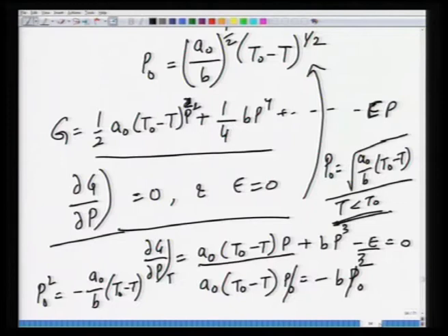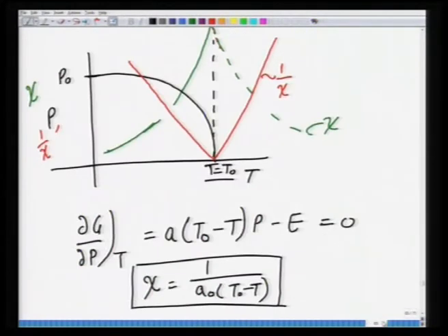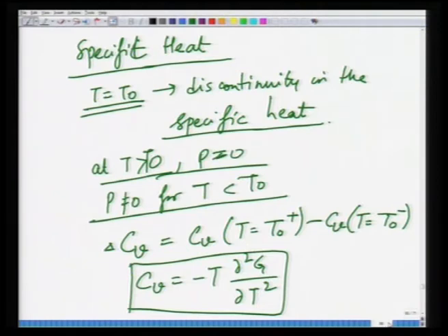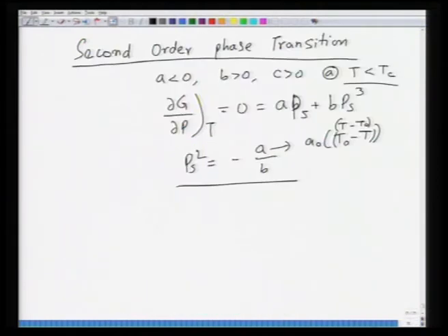From that you get an expression for Ps squared, the saturation polarization near Tc, and then we got the susceptibility near the transition: below Tc and above Tc as 1 over A naught into T naught minus T. Near T naught it goes to very high values, or 1 over susceptibility goes to 0, which is what is depicted in this curve. Then we looked at the specific heat and so on.